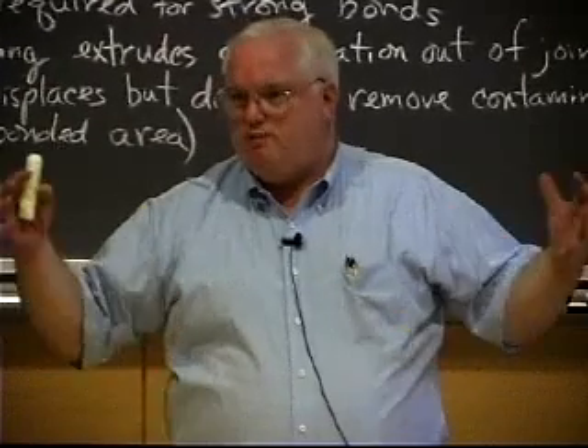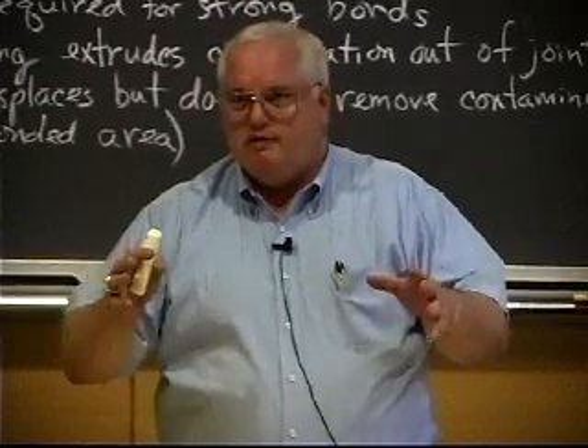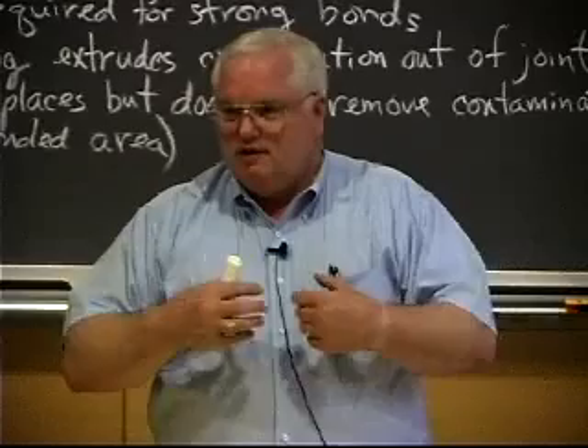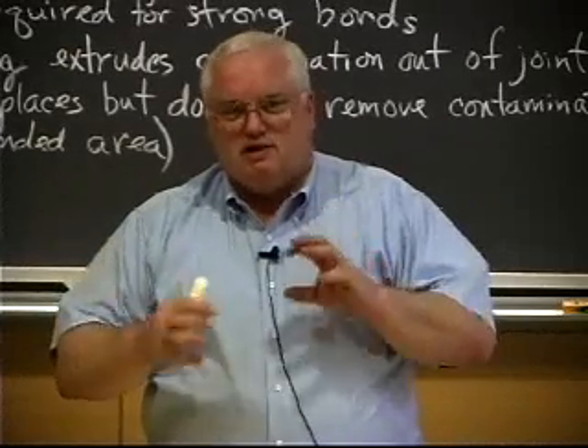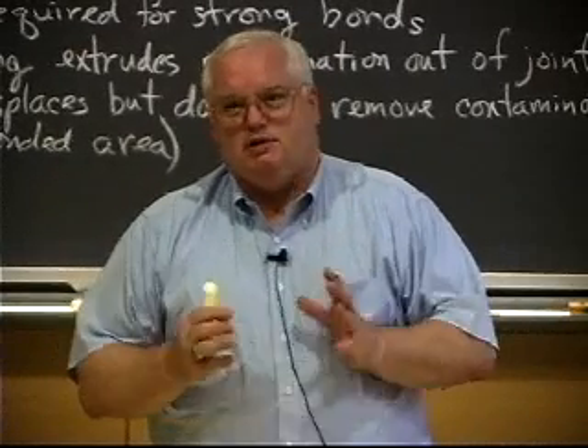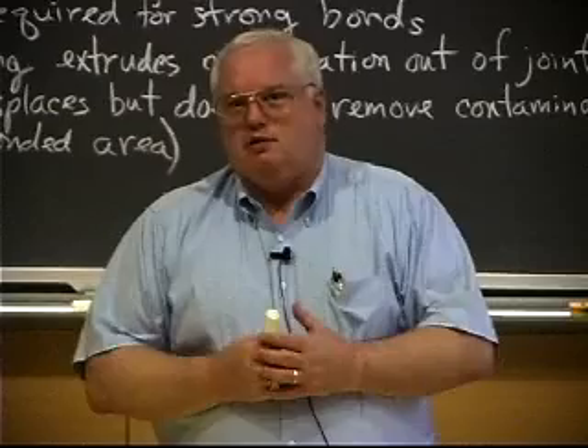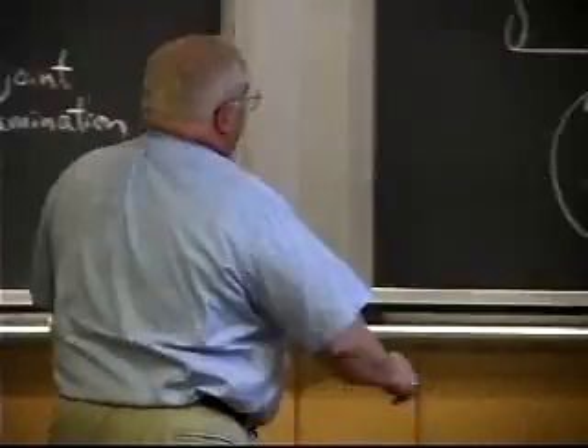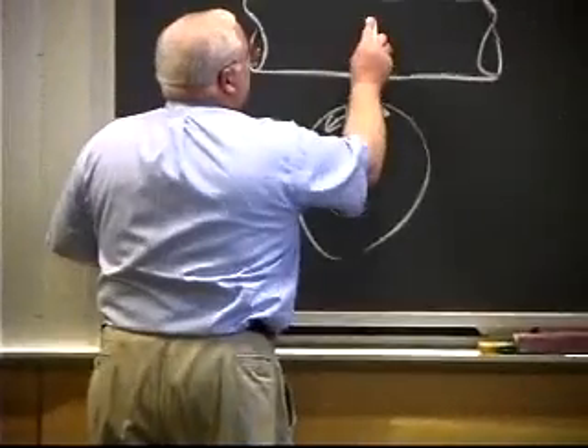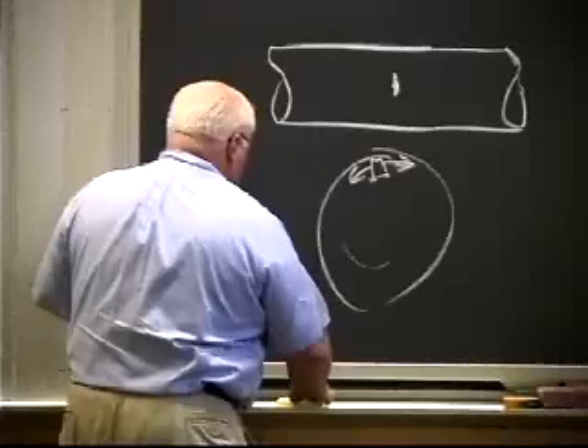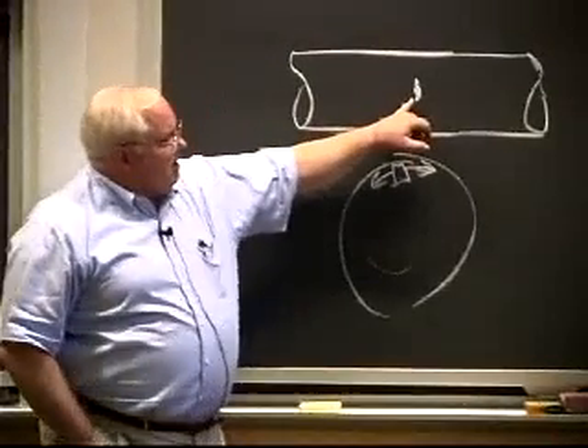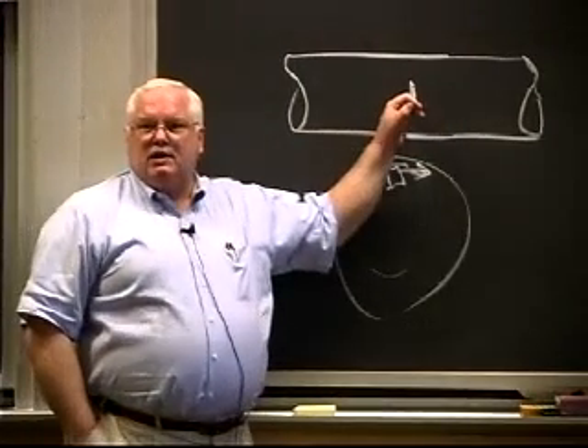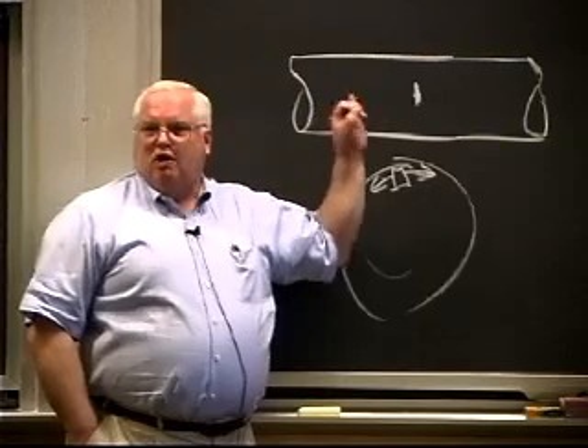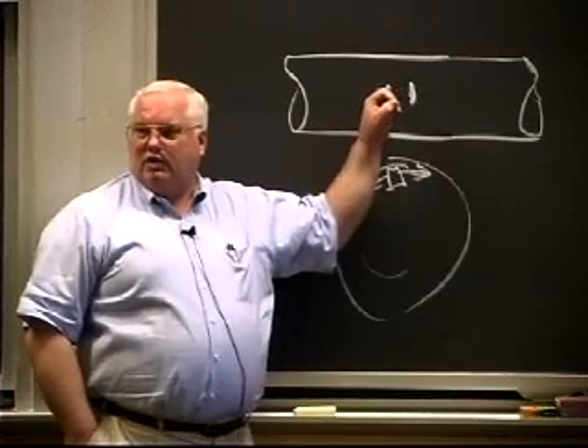When you put a great big thing, put a roast beef in an oven, the outside starts to cook, it expands. The center is still cold, right? And so the two of them are tied together. So in that particular case, the crack that occurred in the shaft on the LNG tanker basically occurred when the metal was cold and the metal was still brittle.